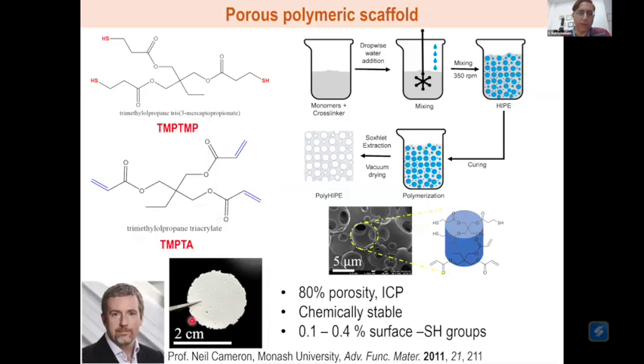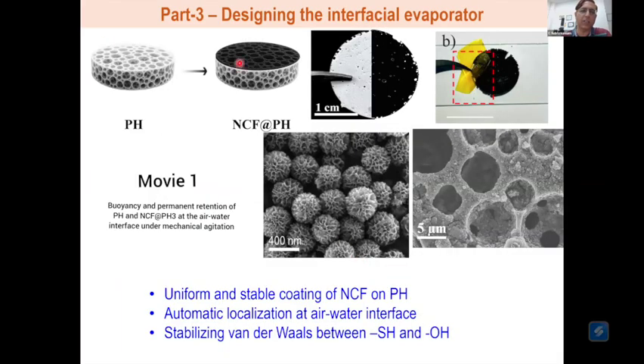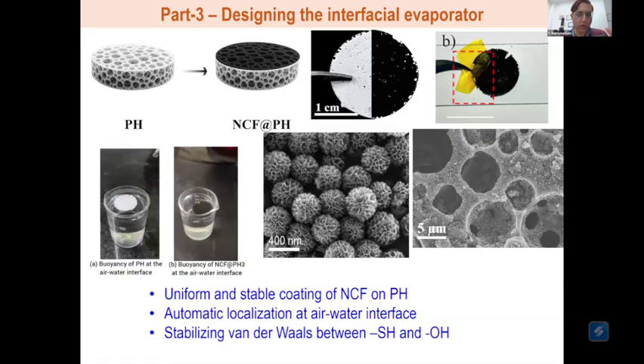So he was the one who made this polymeric membrane or scaffold, a porous polymer scaffold. And we took this scaffold. What was interesting is it's a porous structure, and we coated one surface of this material with NCF, the black material, that is our proprietary material. And the interesting thing is, if you take this material and try to dunk it into a body of water, it self-floats. It's so light and porous that it can actually float even if you push it down inside the bulk of water.